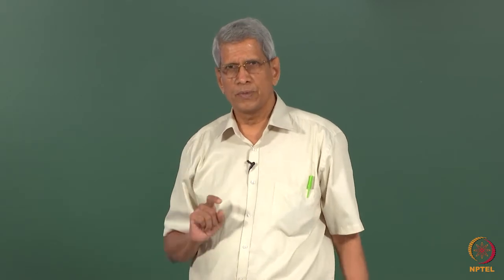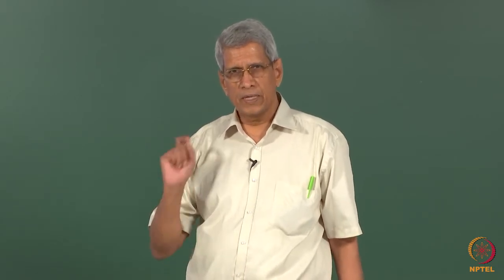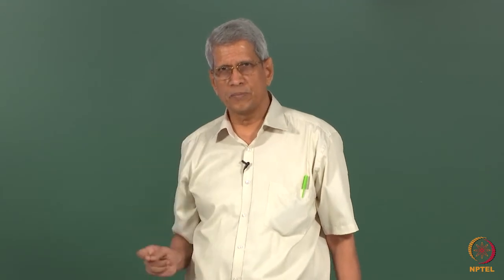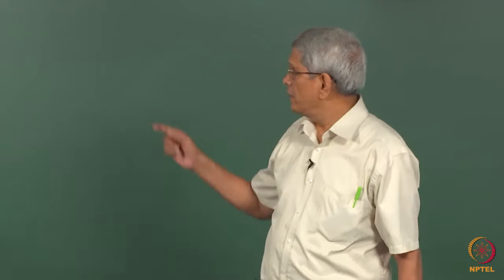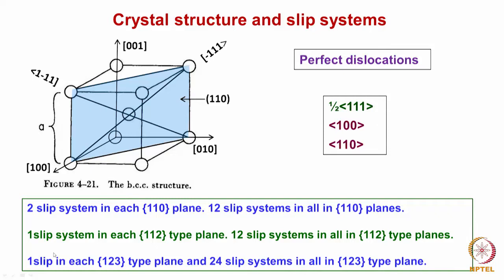There only one 111 direction is there, but there are 12 112 planes, so 12 slip systems are possible. Then if you look at the 123 plane, there is also only one 111 direction, but if you consider 123 planes, there are 24 distinct planes. So if we look at the total number of slip planes available for a perfect dislocation in BCC, there are a total of 48.